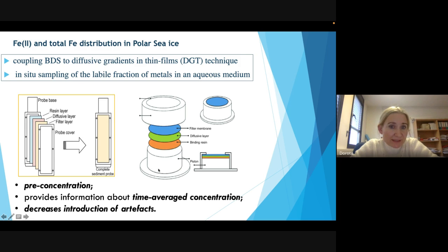In general, they consist of the same parts. We have the upper and lower probe cover. Here we have the filter and diffusive layer that have the role of protective layers, under which we deal with the so-called binding resin, which has the ability to selectively bind, depending on the type of layer we pick, the labile fraction of metal inside it. So the idea is based on pre-concentration of this metal within that layer, and we get time-averaged information about its concentration. In our analysis, we took that layer, deposited it on a glass support and left it for drying before the analysis.